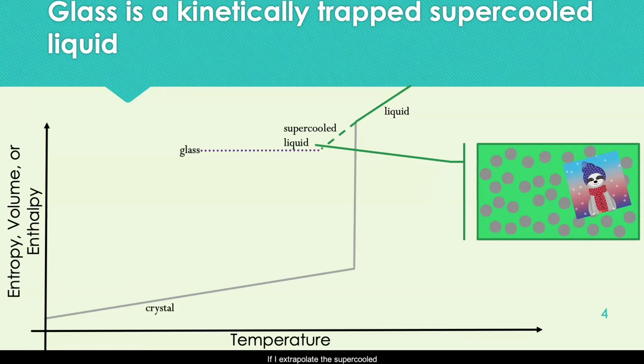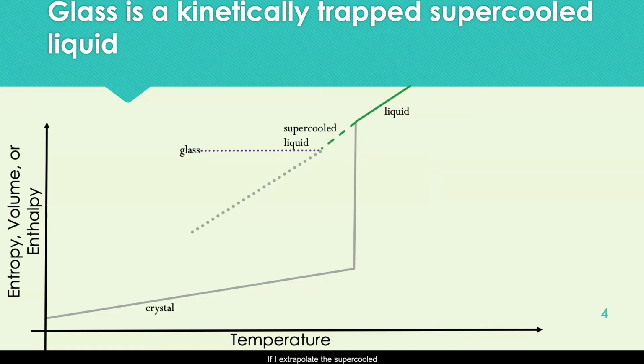And you're right. If I extrapolate the supercooled liquid line and want to move farther down it, I can do so by cooling at a slower rate. So I'll move farther down the supercooled liquid line before the glass is too slow to catch up. I characterize a particular glass by its glass transition temperature, or TG, which is the temperature at which the system starts to deviate from the supercooled liquid line, and is conventionally defined at a 10 K per minute cooling rate.